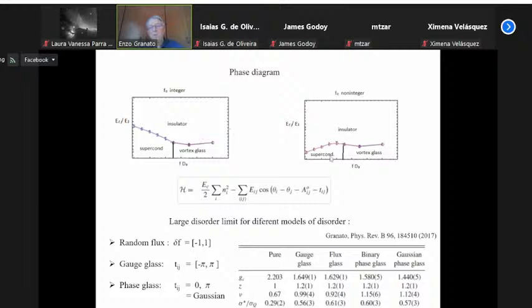And for this particular calculation, we use a particular kind of disorder, a particular distribution of the disorder. But when the disorder is very large, which is the limit to the right here, models with different disorder should roughly give the same result. And so we have done a calculation using different kinds of disorder, like a random flux model, gauge glass model, and phase glass model. And these are the calculations. I will not go into much detail. They all give similar results.